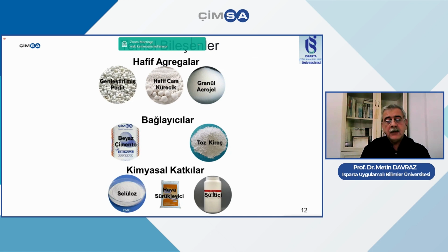And of course, it is also possible to make use of powder lime because the adherence of the material is being increased, and also compared to concrete cement, its coefficient number is lower, 15%, 20% lower. And when we go through the chemical additives, CMC type of powder cellulose, and also we do have dust polymers are present. These are the basic two components.